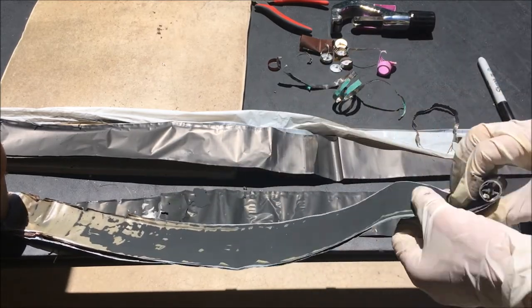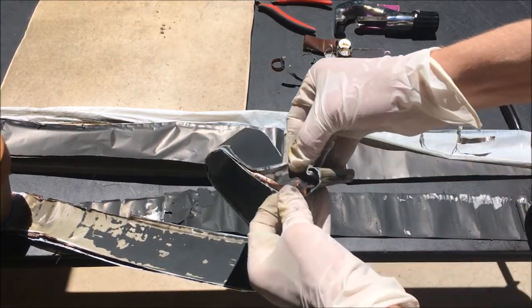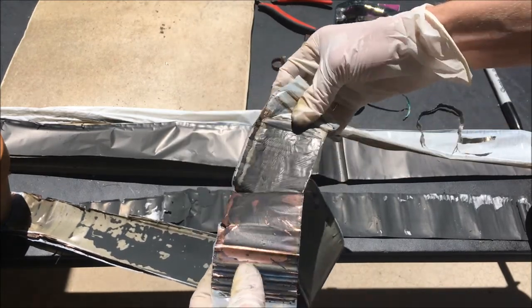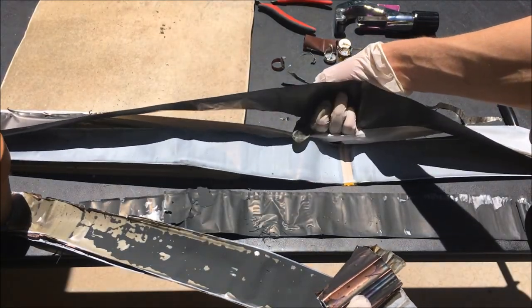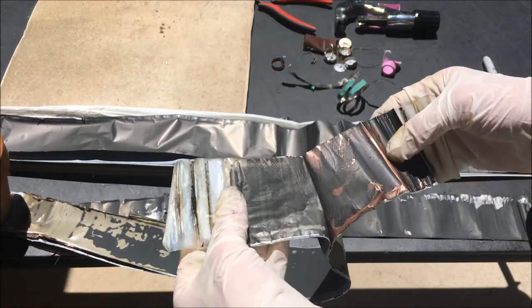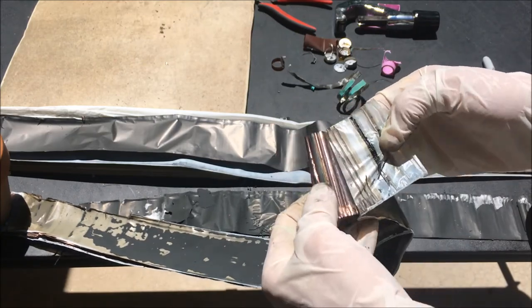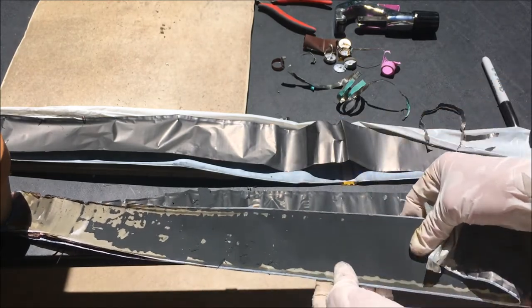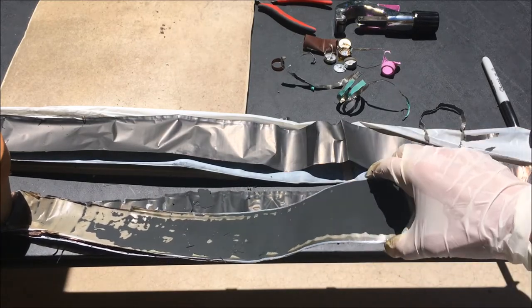If we actually separate these further, you can see there's a sort of copper conductive layer in between. Whereas the LG cell had that copper layer kind of integrated, in this cell the copper layer is sort of just not completely stuck on. It's kind of incorrectly bonded between the separator layers. It's got all these ripples and bumps in it, and really generally you can see the quality of construction of the cell is much less.